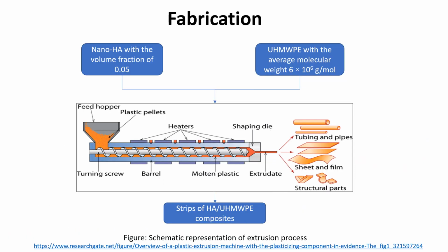The strips of the hydroxyapatite ultra-high molecular weight polyethylene composite will be produced using the same method. The powder of nano hydroxyapatite with a volume fraction of 0.05 and ultra-high molecular weight polyethylene with an average molecular weight of 6 x 10^6 g/mol will be compounded using the twin screw extruder. Rotation speed will be set at 420 rpm and the preparation time will be around 180 seconds.